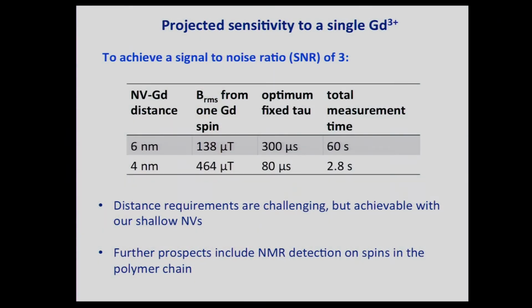And just to give you some idea of what types of sensitivity we expect: if we can bring that single gadolinium to within 4 nanometers of the NV center, and we can grow NV centers within 2 to 3 nanometers of the surface, we should be able to get an SNR, a signal-to-noise ratio, of 3 in about a 3-second measurement. It's very sensitive to separation. For 6 nanometer separation, it would take us about a minute to get an SNR of 3 to detect a single gadolinium spin label. And other prospects include NMR detection on the spins in this PEG polymer chain too. That's another thing we're thinking about doing.